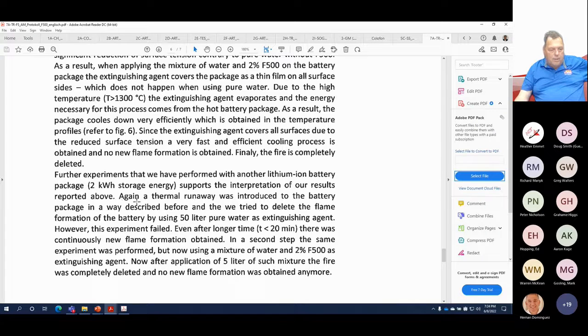results reported above. Thermal runaway was introduced to a battery as described, and we tried to delete the flame formation of the battery using 50 liters of plain water as the extinguishing agent. However, the experiment failed. Even after a longer time of 20 minutes, there was continuously new flame formation. The second step was the same. So what they're saying here is the first time we used 50 liters, the second time 5 liters.